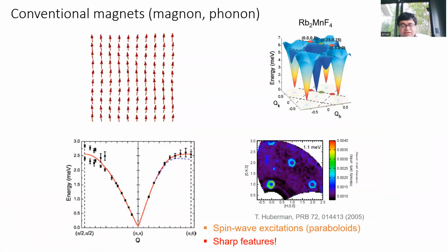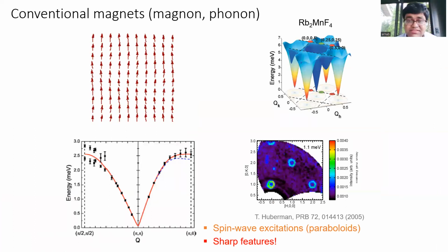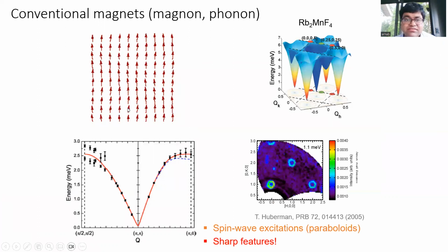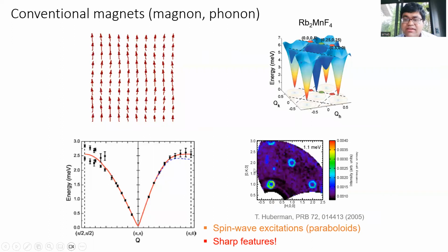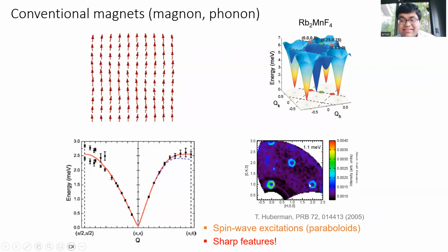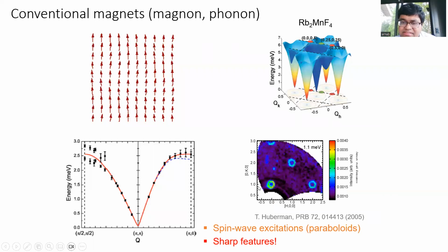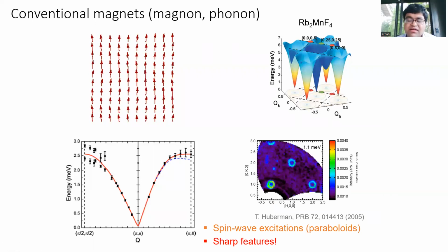One of the final things I will say about neutron scattering is that in conventional magnets, you get magnons and phonons, so this is basically a magnon mode. If you do the Fourier transform of that, and then the neutron scattering analysis, you look at the neutron data, which shows 2 reciprocal lattice directions, where red is more intensity and black is less intensity. What you get is these nice cones, and these cones come from the parabolas, which are directly related to the magnon or the phonon dispersions. So that's how the data looks.